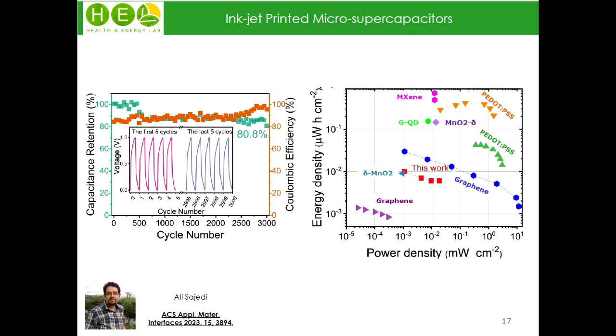So we have a delta phase with more capacitance and a delta phase with less capacitance, and the difference in this system is mainly the interaction of the electroactive material with the electrolyte. We suffered from the gel electrolyte in this work, and that was the reason that limited our capacitance, power, and energy density—not the phase of manganese oxide.